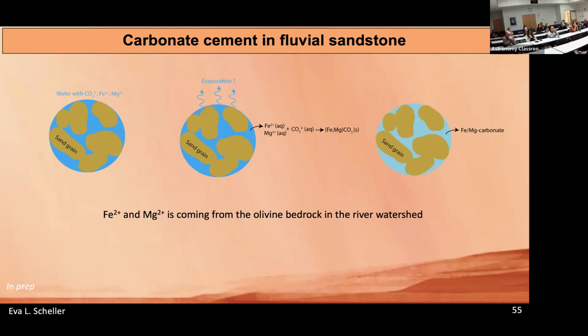Again, you need to have a fluid with dissolved CO2, iron 2 plus, and magnesium 2 plus, which is what we observe in the carbonate. You need some way of reaching saturation in the fluid. Now, the most common way to do that is through evaporation or just having a lot of dissolved material in very little fluid. And you can easily get this iron magnesium carbonate to precipitate out. That is something that very commonly occurs when you have olivine in the watershed of your fluid, because you get this right mixture of the iron 2 plus and the magnesium 2 plus, and you have lots of olivine bedrock, thought to be similar to this crater floor material, in the watershed of this river.